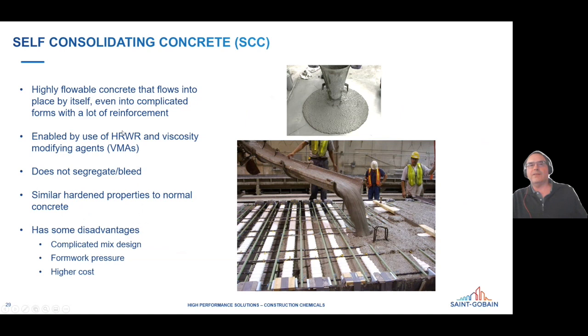So this is one of the categories of concrete, self-consolidating concrete, that's really only been possible since the high-range PCEs have been developed. And so this is a highly flowable concrete that really reduces the amount of work that it takes to place it into a complicated formwork. So essentially, it's so flowable that it spreads out and fills all the spaces under its own weight, because it has a very low yield stress. Now, you could do that just by adding a lot of water, but then you would have terrible problems with segregation and bleeding, and then you would also have very low strength development. So that actually doesn't make any sense. So here you're able to have the very high flow, but yet once it hardens, it has the same kind of strength development as normal concrete.